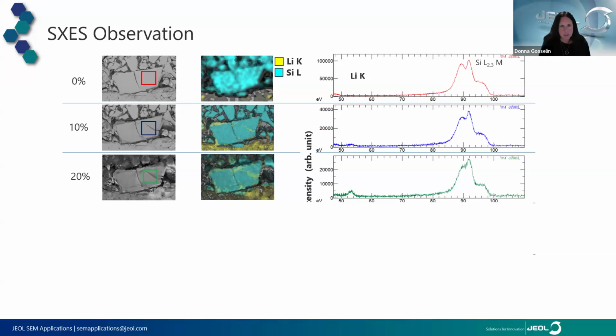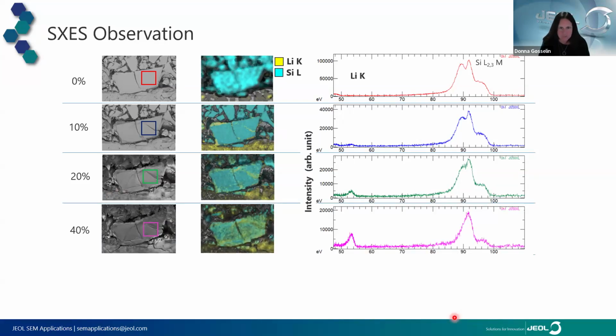When we move to 20% charge, that peak intensity of the lithium is increasing. So we're seeing a little bit more of the lithium intercalating into that silicon particle. And we're seeing some more subtle changes in the silicon L peak shape. And again, that's corroborated, which is nice, with our X-ray data and our backscatter electron image. At 40% charge, we see a more dramatic increase in the lithium concentration. We also see a little bit of a shift in the lithium peak position, indicating that we might be alloying with the silicon particle. Again, the backscatter and the EDS maps are corroborating that data.